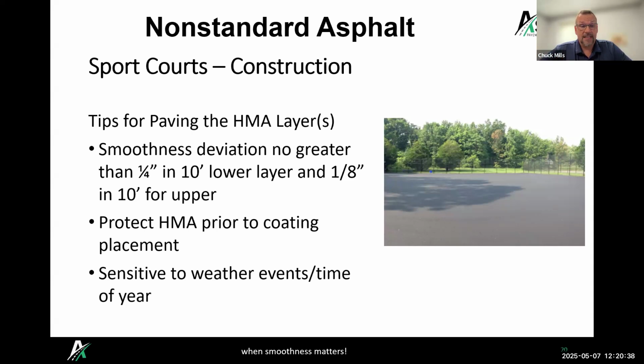We want to protect the asphalt prior to coating placement. We don't want it getting all dirty. Typically, you've got to wait about 45 days to put the coating on after the asphalt. You want to give that asphalt time to cure so that the coating can stick properly. So keeping that asphalt surface clean gives you a better chance that the coating is going to adhere to it properly.